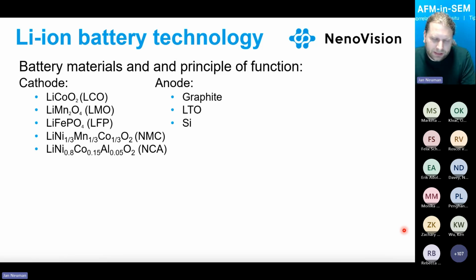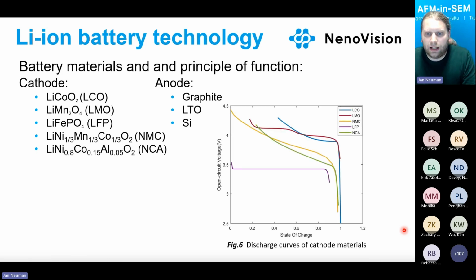A big advantage of lithium-ion batteries is that we have quite a lot of materials which can be used on the anode and cathode side. Each of them has different properties, like electrochemical behavior and, for example, thermal and structural stability. So we can set the properties of the battery based on the materials we use on the electrodes. In figure 6, you can see the different discharge curves of cathode materials. As you can see, the working potential is different if we have lithium iron phosphate or lithium nickel manganese cobalt oxide.